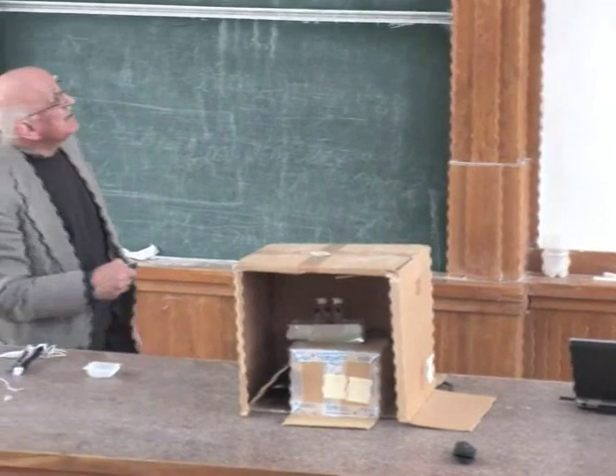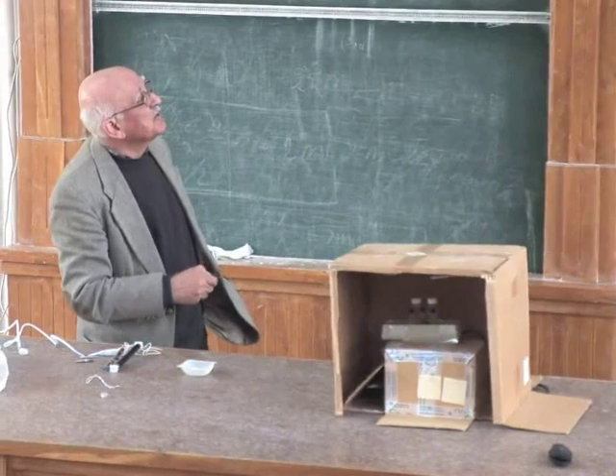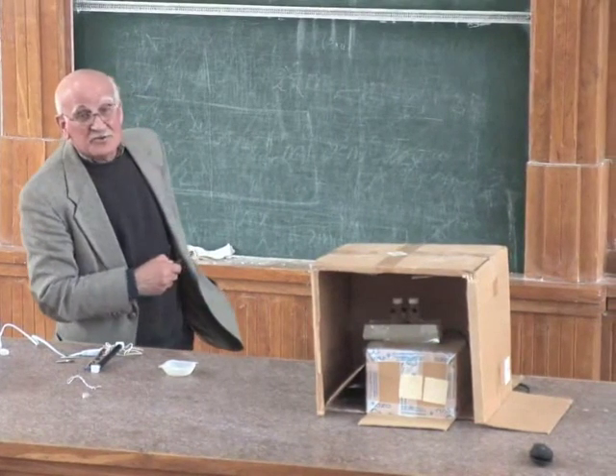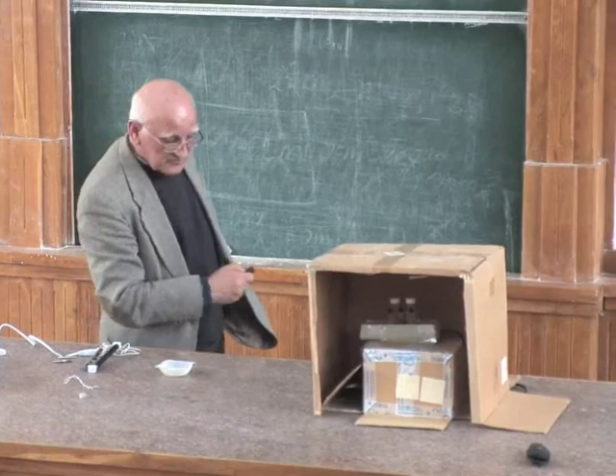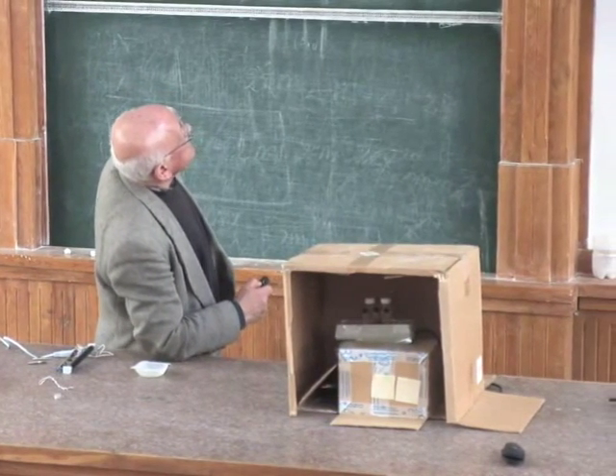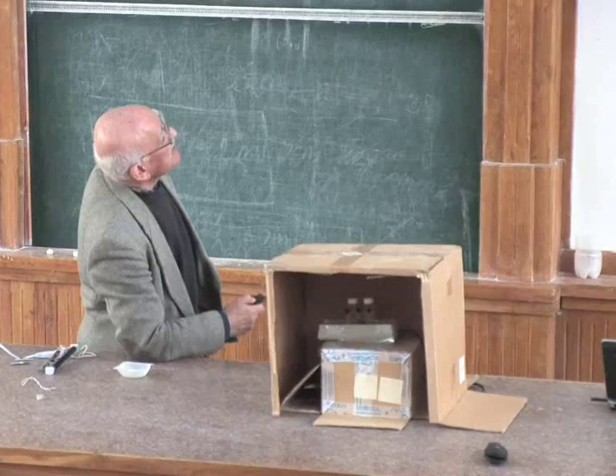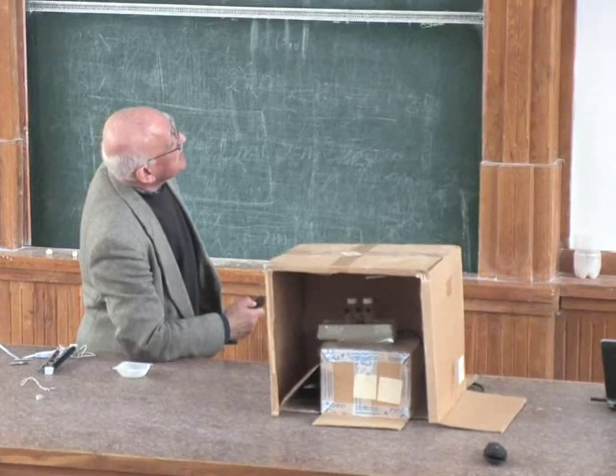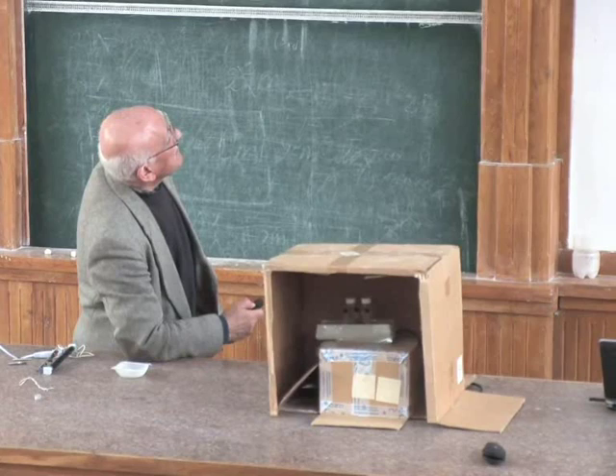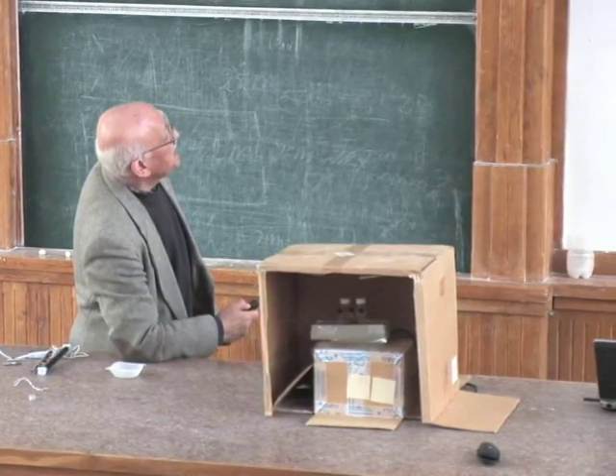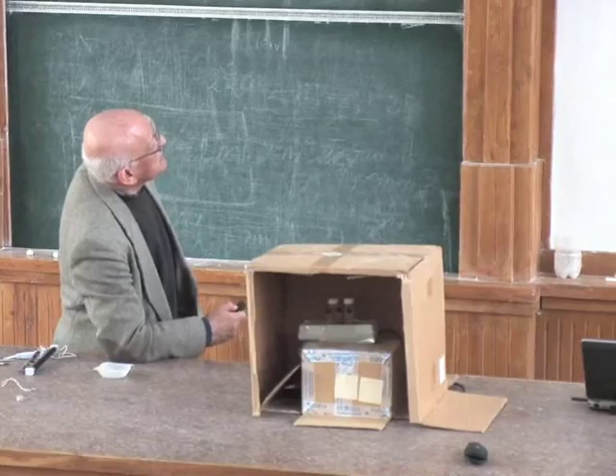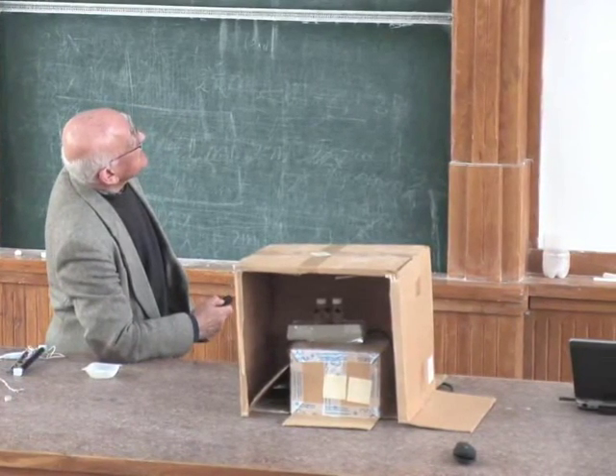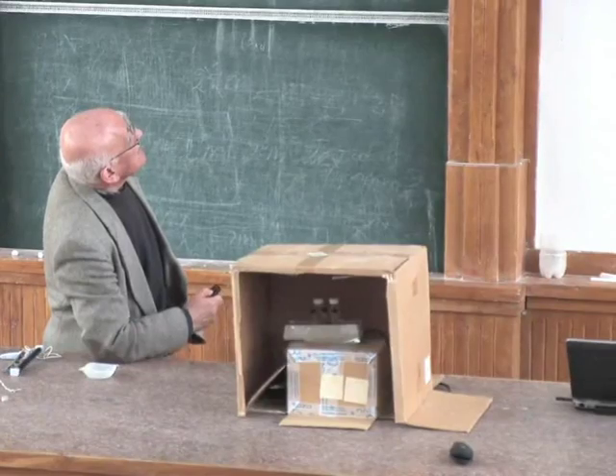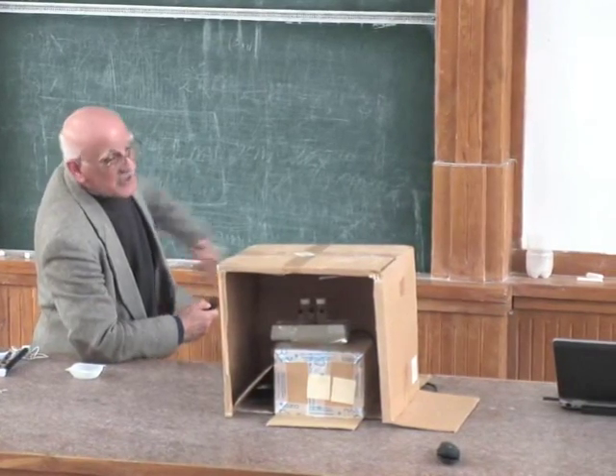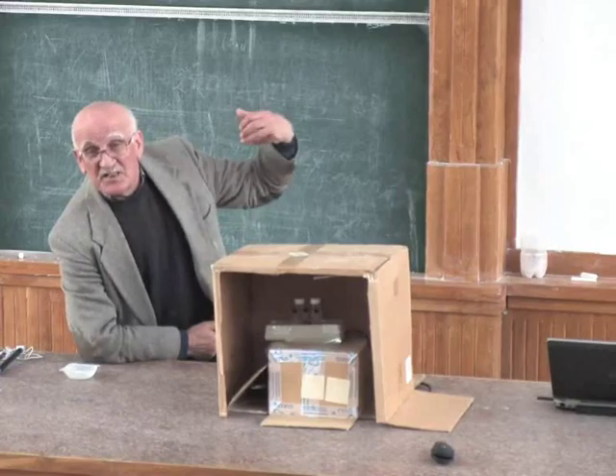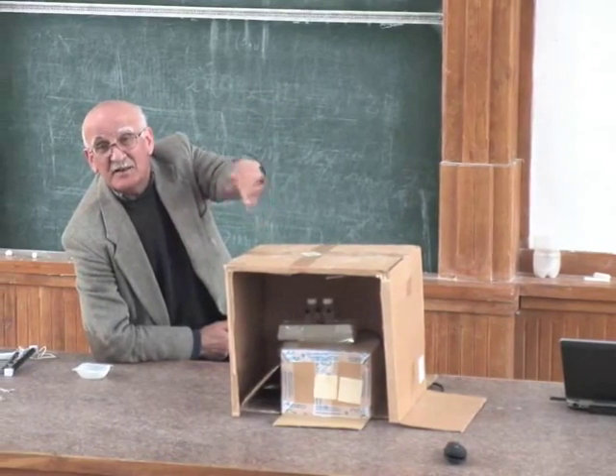Here is another polymer for drug delivery, and this is what Yulia, under the direction of Gorin, is also doing. So we prepare the calcium carbonate structures, microstructures. They could be amorphous or crystalline looking. If they are amorphous, they have pores. Then we incubate the nanoparticle. We put these in the nanoparticle solution like that, and wait.